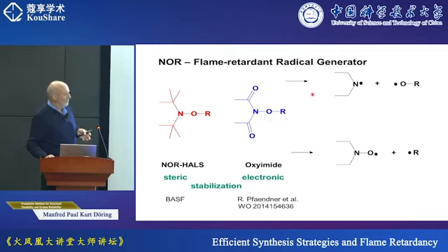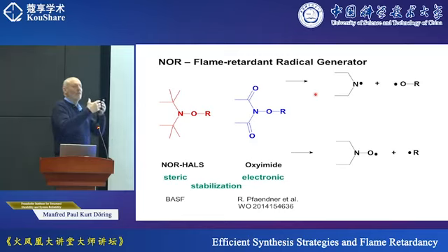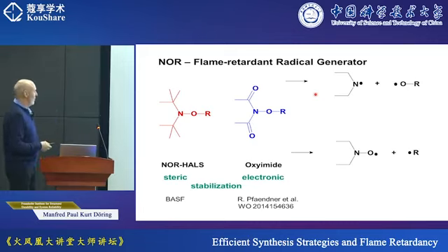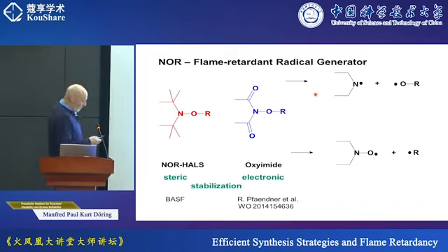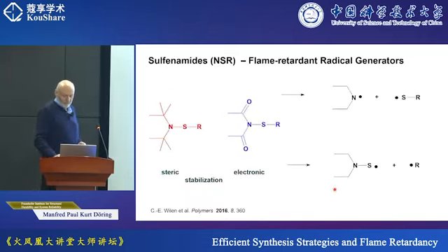If you do this or this, you will be able to stabilize that molecule for bringing it into your polymer and guarantee durability and reliability. But on the other hand, if fire comes out, these radicals will be formed and can catch our OH and H radicals.